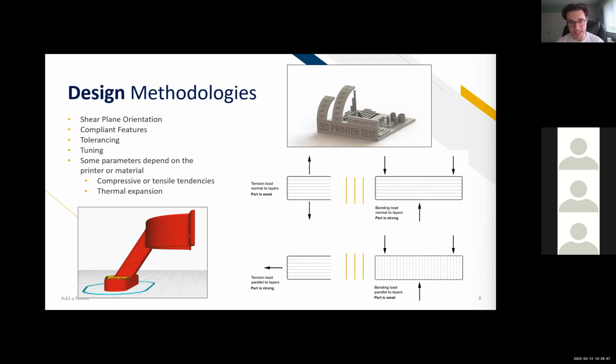And essentially, a single layer of a 3D printed component is strong if it's in tension, if you pull it across its axis. When you have multiple layers stacked up and you pull that part in its orthogonal direction, so a direction which is perpendicular to the plane that was just printed, it is incredibly weak. So one thing when you're setting it up and you're designing your component in CAD is you want to avoid features which would essentially force you to have to create a part which would take compressive or tensile forces in one of these directions here.